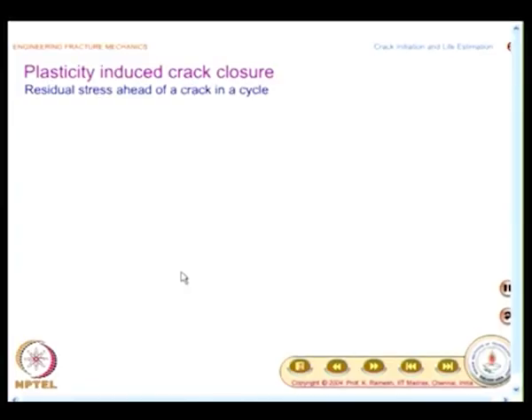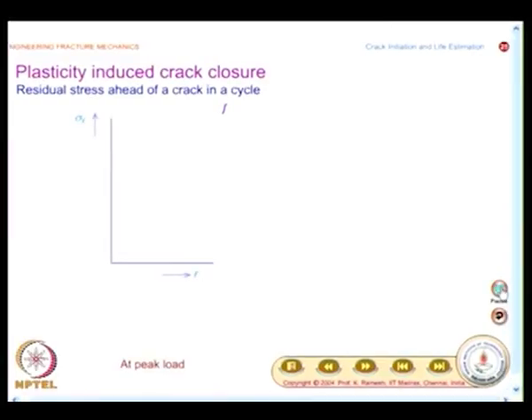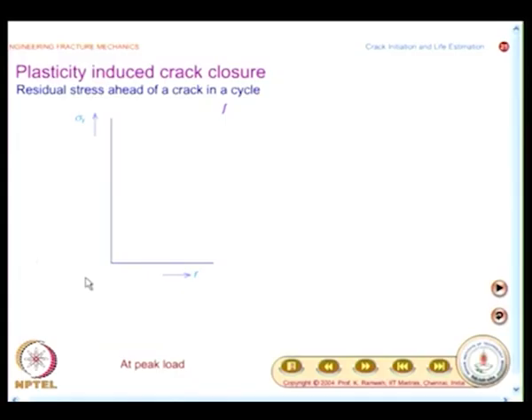Now, what we will do is, we will try to go and understand what is crack closure. There are various categories of crack closure, and we will first see plasticity induced crack closure. And the first concept that you have to learn is, what is the residual stress ahead of a crack in a cycle. What is shown here in a tiny fashion is actually when you have a sinusoidal load, you are looking at one half of the curve where you are going from 0 to maximum. So, when I go from 0 to maximum, we would see what happens at the crack tip.